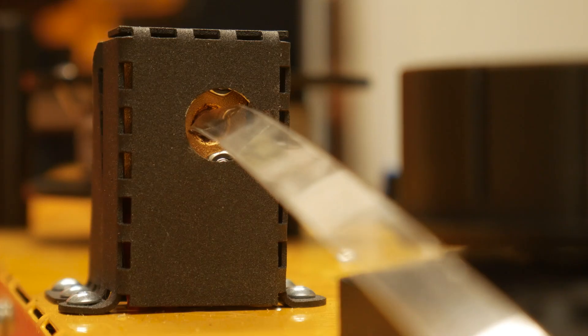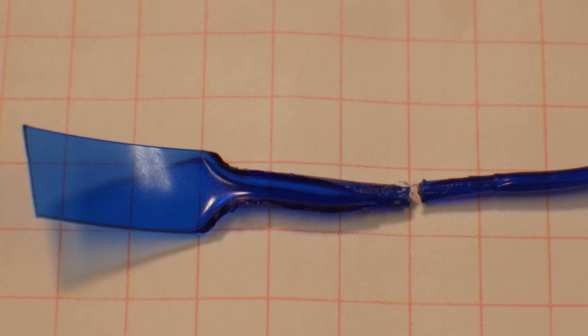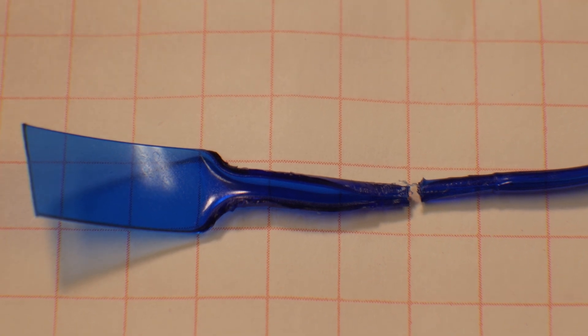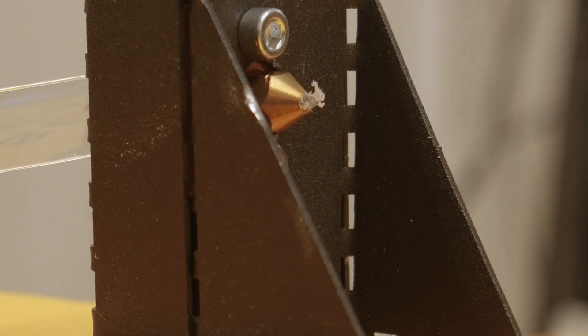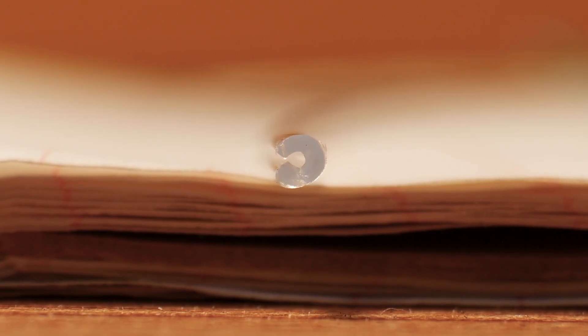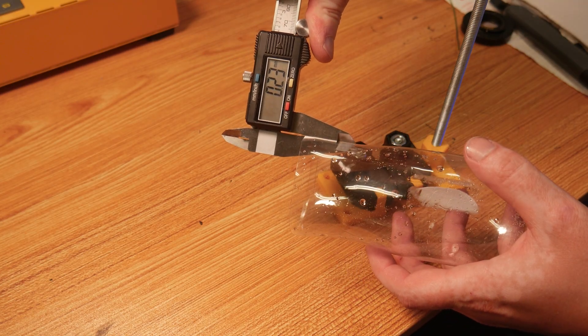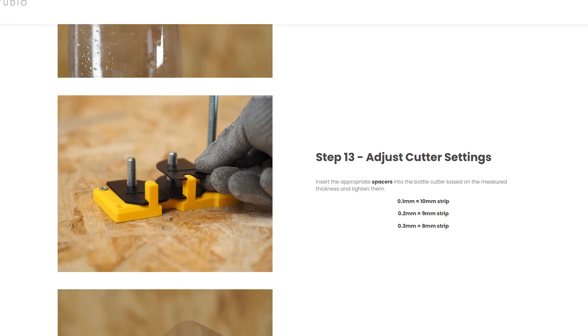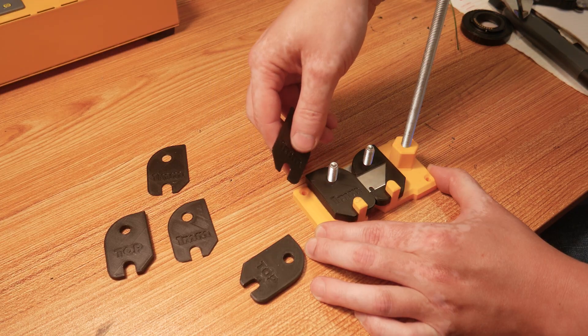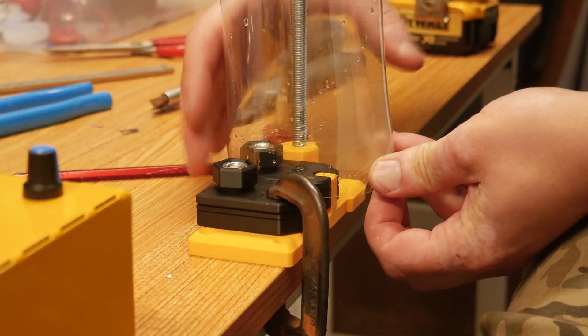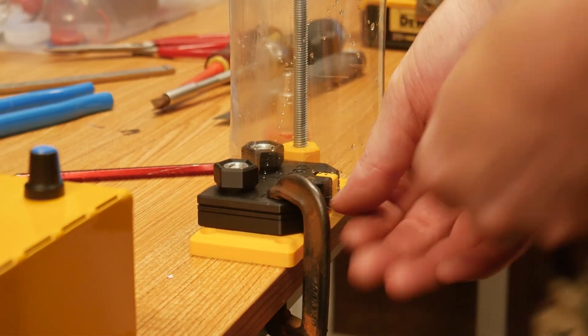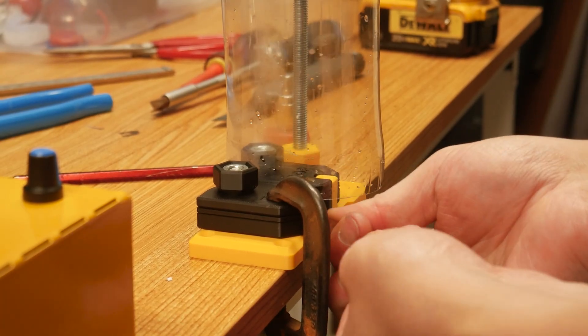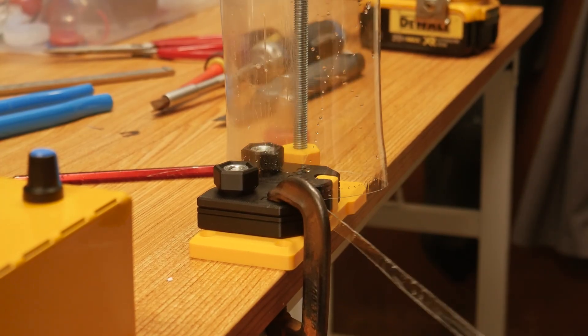The width of the strip is crucial and depends on the thickness of the bottle. The PET filament maker reshapes the strip into a tube, so ideally we want enough material to create a full, hollow tube. Too much material can jam the extruder, and too little will result in filament that looks like this, making it harder for your 3D printer's extruder to grab. After measuring the bottle thickness with calipers, you can refer to the chart on the Sustainable Design Studio website, set your filament cutter using spacers, and feed the bottle tail into it. Pulling the strip through the cutter can be tricky at first, but once you get the hang of it, it's actually super satisfying.